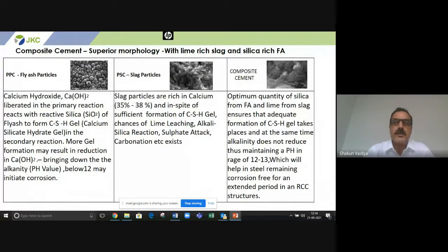So composite cement is a futuristic blend of slag and silica. It has that pH balance technology, where a shortage of calcium hydroxide, if it is totally consumed in PPC, may result in lowering of the pH value, which should not go below 12, which may initiate corrosion. And in slag, an excess of lime may also result in leaching, free lime and alkali silica reaction.